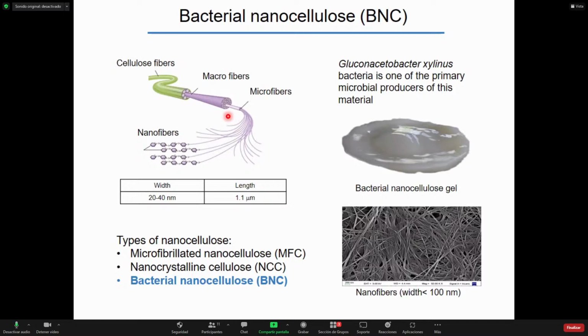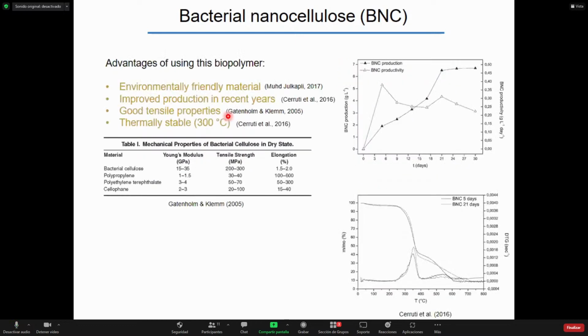In this case, the Gluconacetobacter xylinus bacteria is one of the primary microbial producers of this material. On the macroscale, this material looks like a gel, but on the microscale, there are actually cross-linked nanofibers. Some advantages of using this biopolymer are that its production is environmentally friendly, and its production has been improved over recent years. It also has good tensile properties when we compare it with other polymers, and is thermally stable up to 300 degrees Celsius.